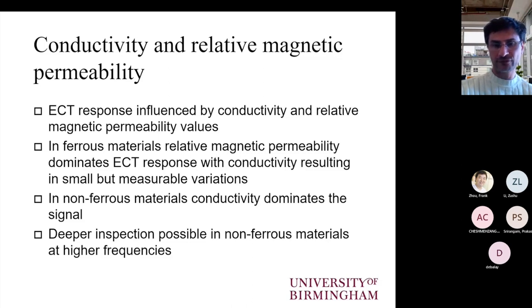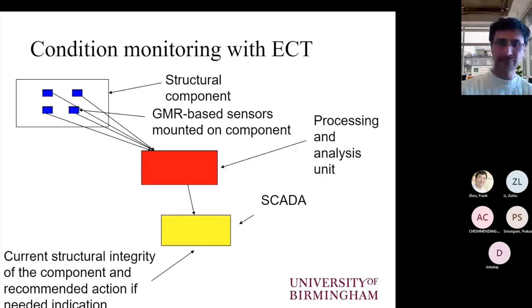Of course, the depth of the inspection will depend on the conductivity and relative permeability values. So when the phase transformation occurs, we have to take into account that the depth that we're inspecting is also changing with time. So we have to take this effect into account.